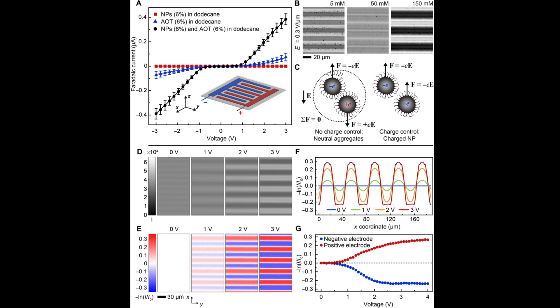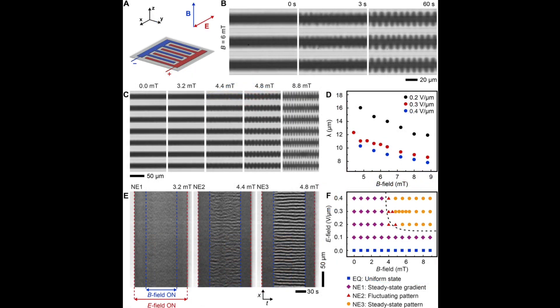This electrical responsiveness causes the nanoparticles to migrate, and the resulting differences in nanoparticle concentration change the magnetic responsiveness of the electro-ferrofluid. As a result, applying a magnetic field across the electro-ferrofluid changes the distribution of the nanoparticles, with the precise pattern depending on the strength and orientation of the magnetic field. In other words, the nanoparticle distribution is unstable, shifting from one state to another driven by a small change in the external magnetic field. The combination of voltage and docusate transformed the fluid from an equilibrium system into a non-equilibrium system that requires constant energy input to maintain its state.